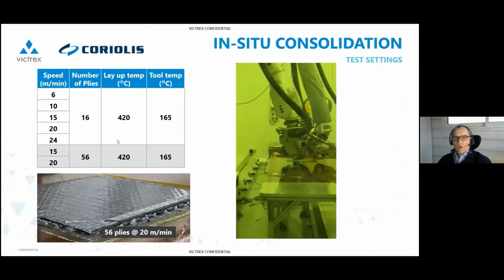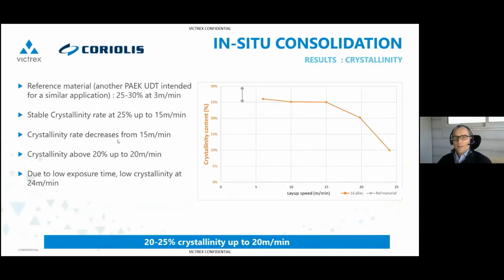For the in-situ, we worked with, and you will see, both Coriolis and Electro Impact, but the first section is with Coriolis. So Victrex and Coriolis wanted to tackle the processing benefit of the Victrex AE250 UD tape for in-situ. So we set a range of parameters. We worked on the speed, the temperature, the tool temperature, and we wanted to really make this part by in situ, and then evaluate the quality of the laminate. When you look at in situ, you want to pay attention to three things: crystallinity, porosity, and mechanical strength, and that's what you will see on the next slides.